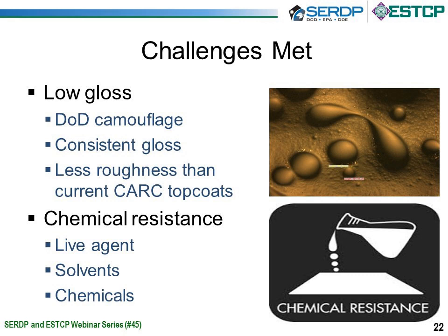This helped us obtain consistent gloss, and realistically, even though I said some surface roughness is needed to get low gloss coatings, when you have a lot less pigment than liquid systems, you can get a very smooth coating for a low gloss coating. The chemical resistance, we screened with MEK solvents in the clears. Once we pigmented, this was sent for the official chemical warfare resistance testing. Results sent back through Army Research Lab, and we were able to pass all the requirements. So there is complete acceptance of all the data performed by Army Research Lab, and we're happy to say we are on the qualified products list.